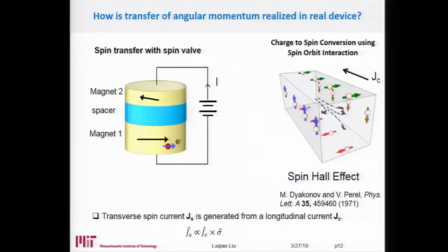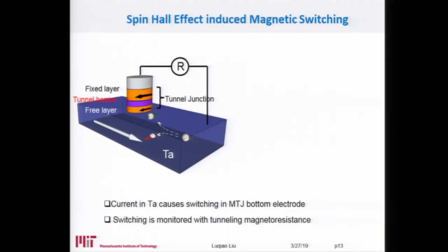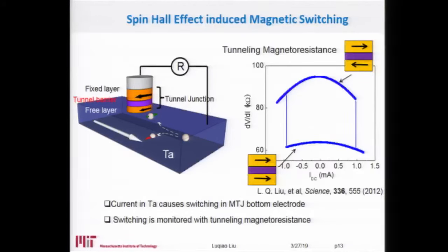But today I'm going to utilize another mechanism, which is known as spin Hall effect. The spin Hall effect was discovered about 4 decades ago, where people demonstrated that when you apply a current inside a material with strong spin-orbit coupling, you'll find that spins will get deflected towards different directions, and they will accumulate at different surfaces. So basically, this gives us a mechanism where we can generate spin current out of a longitudinal charge current. A few years ago, I demonstrated that we can utilize the spin Hall effect inside heavy metals, for example here tantalum, to switch the orientation of the adjacent ferromagnet layer. So basically you apply current in the heavy metal layer, and then through the generated transverse spin current, you can switch the orientation of this bottom free layer, either to make it in the anti-parallel state or the parallel state.